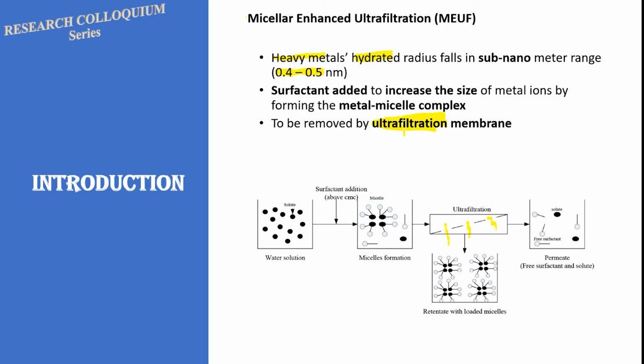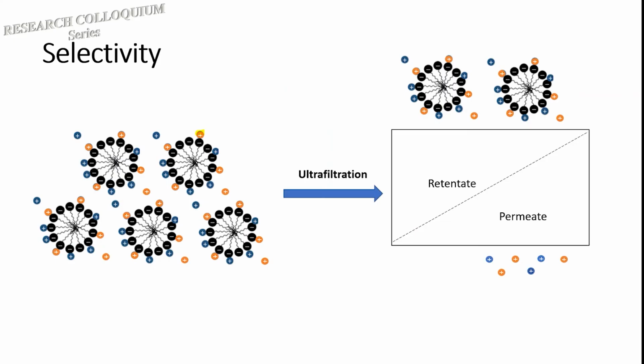That's why in this project, we are proposing using a surfactant, which is added into the ultrafiltration process in the solutions in order to increase the size of the metal ions by forming metal micelle complexes. In general, this process is called micellar enhanced ultrafiltration. Actually, this is not a new concept. Previously, a lot of works have reported the use of MEUF, micellar enhanced ultrafiltration, in removal of heavy metals. But what they did is that they put in a lot of SDS into the solutions. They put the SDS in excess.